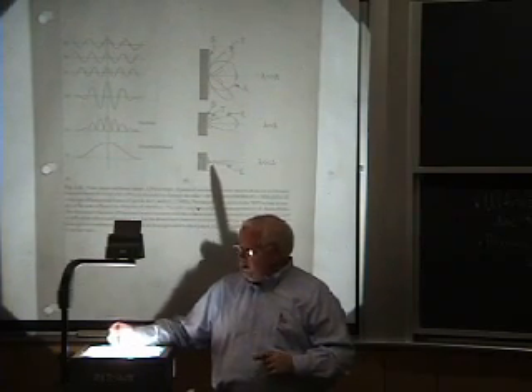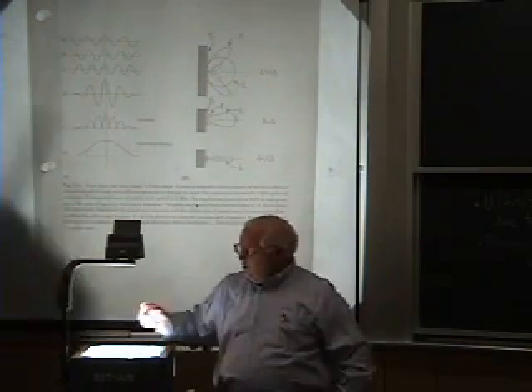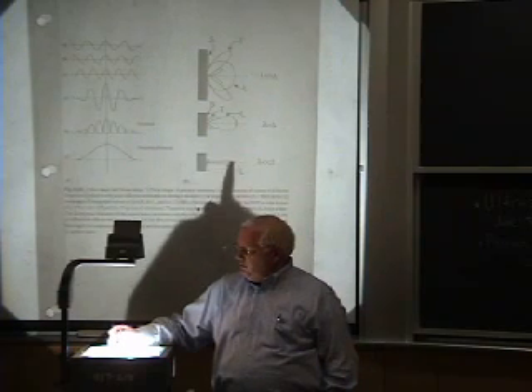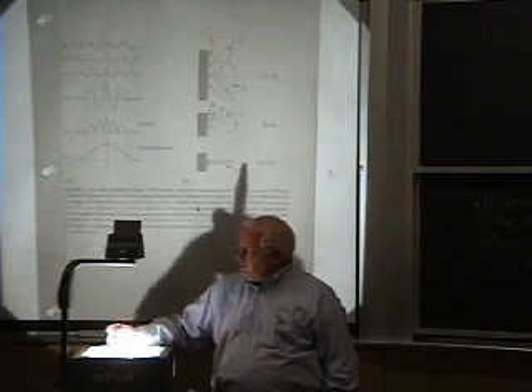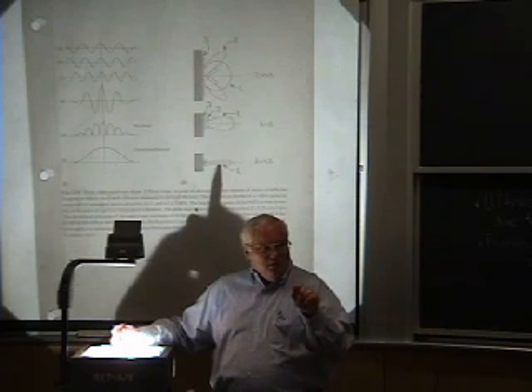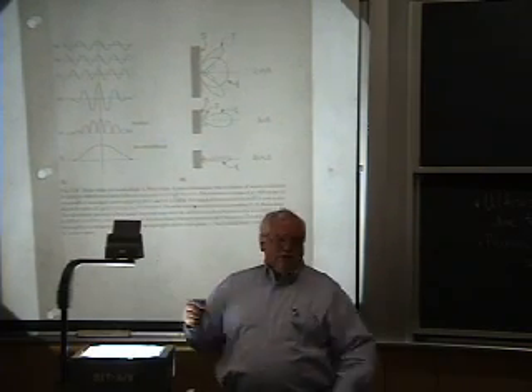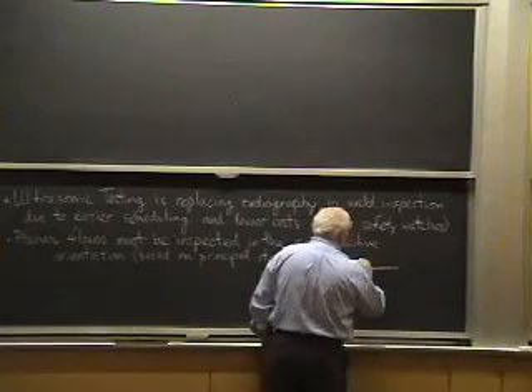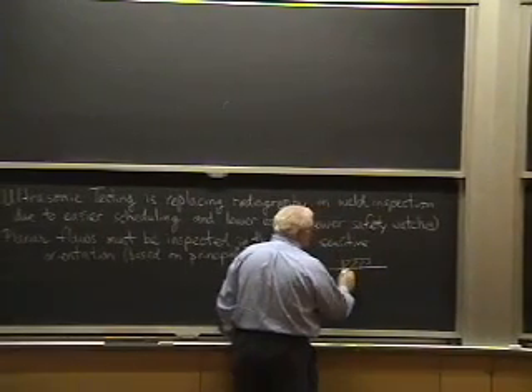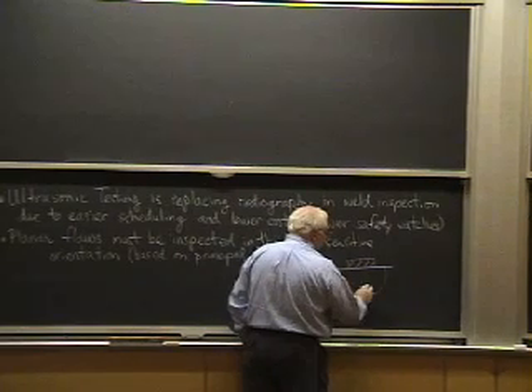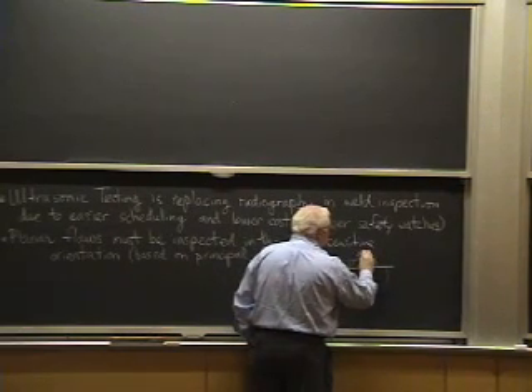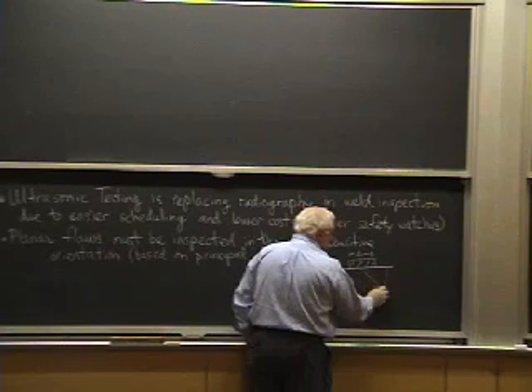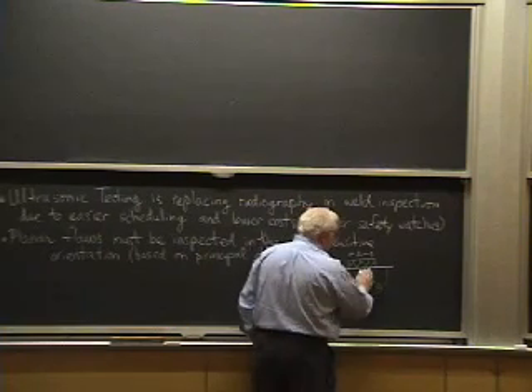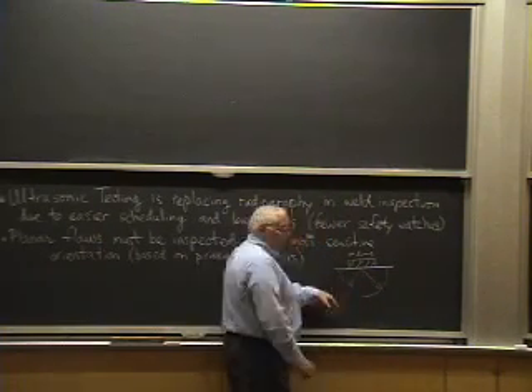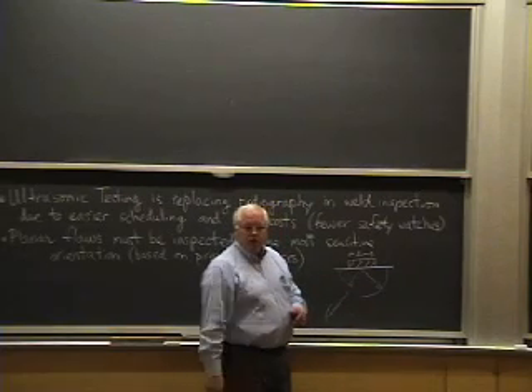In ultrasonics, it's just like taking a searchlight and pointing it around. You may have some small side lobes, but this is supposed to be a polar plot of the intensity of the beam. Basically, this is a sharply focused beam when you get a reasonable distance away from the source. Delta is the width of the source. Once you get one or two deltas away, you have a nice sharply focused beam, and you can point it around your object.